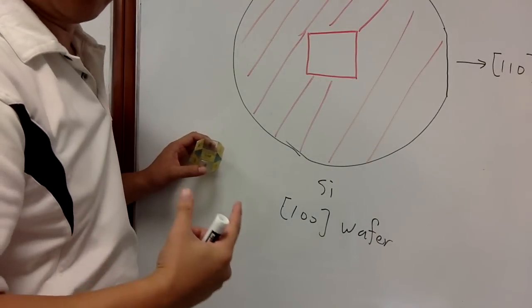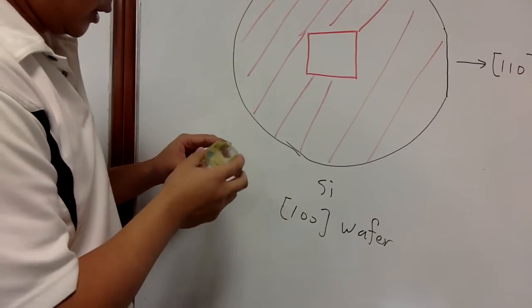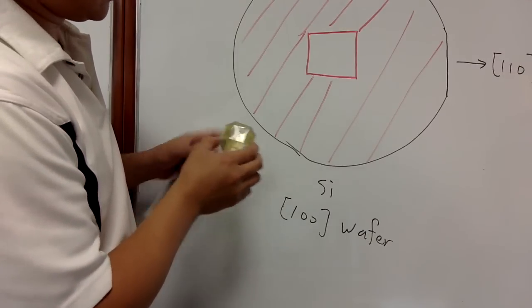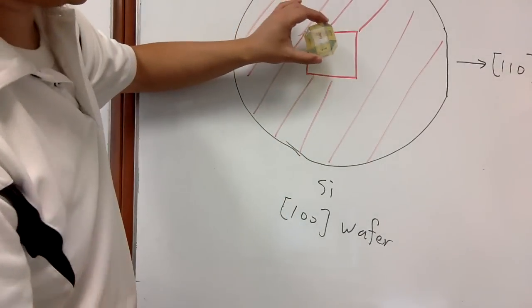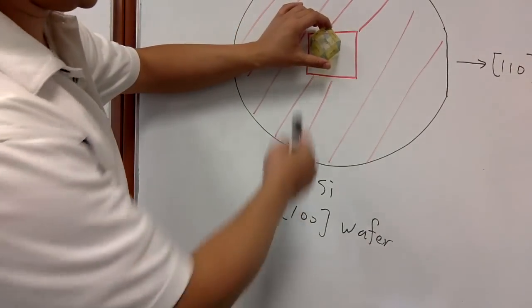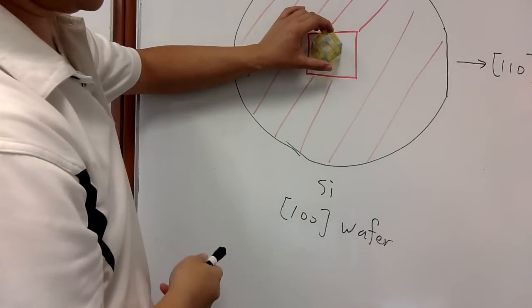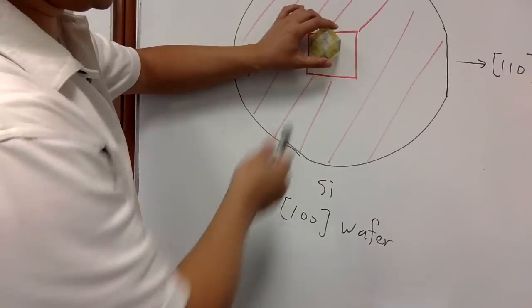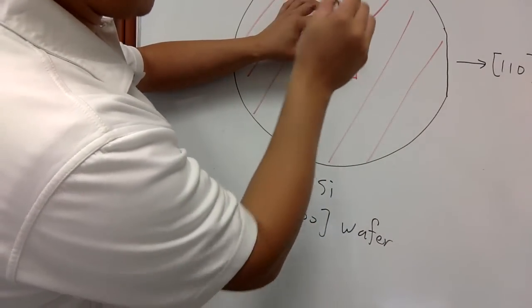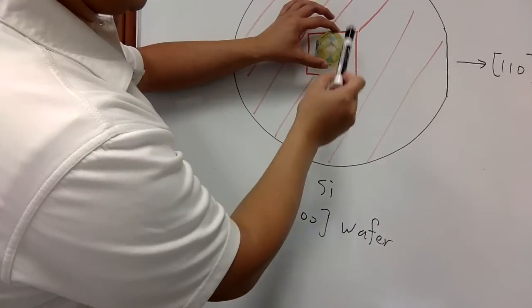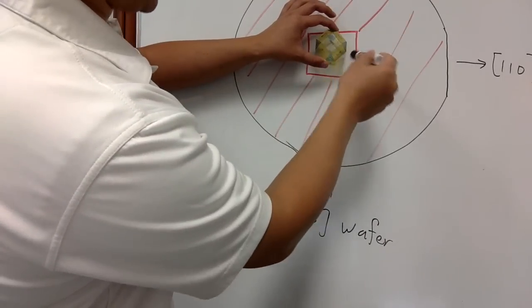The first thing you do is find your crystalline orientation — the same thing we did before. You have the [100] wafer aligned, and the yellow is [110] aligned in that direction. After this, you start to find where the [111] directions are. You have four of them. Because you are looking down from the wafer, you only see the four [111] directions on that side.